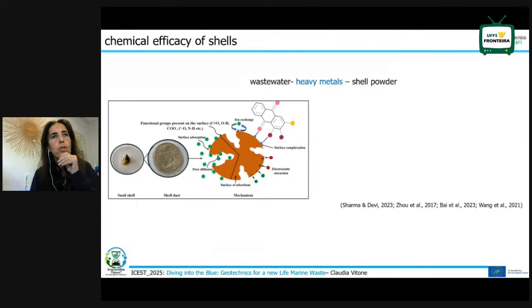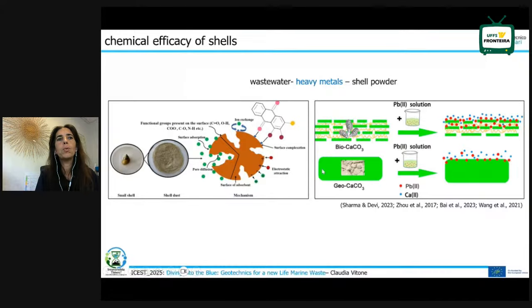But also from the literature in the agricultural world, we find the efficacy of the shell powder in wastewater treatments, since the shell powder has been observed to be very effective to activate several processes to block the contaminants, in particular heavy metals, due to different processes again: surface complexation, ion exchange, electrostatic attraction, etc. And in particular, from a comparison between the shell powder and the limestone, we see that there is even more efficacy if we use the biogenic calcium carbonate, so the shells, because of the brick and mortar layers of this structure.